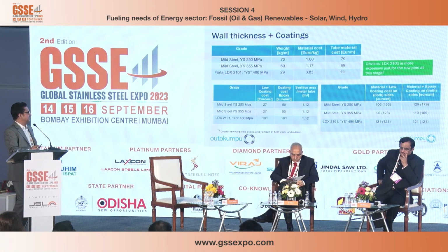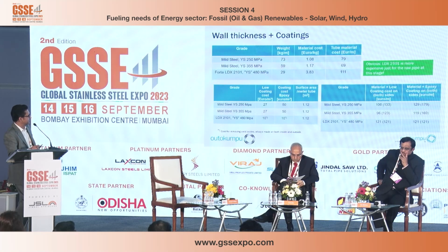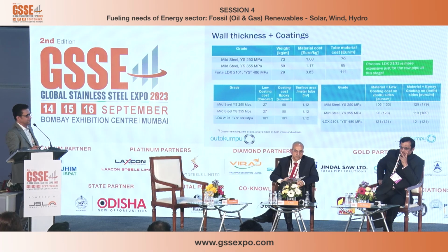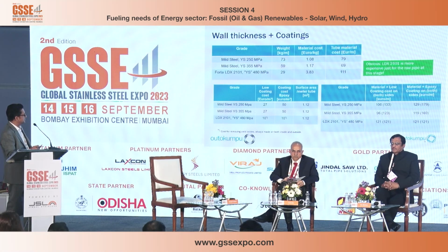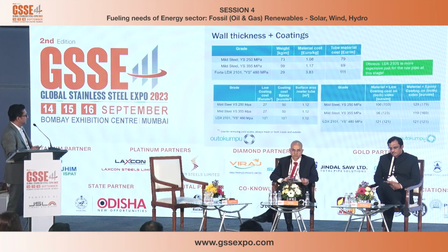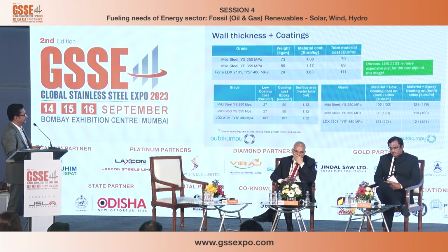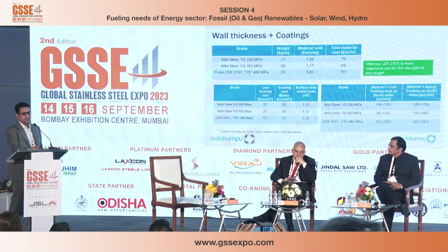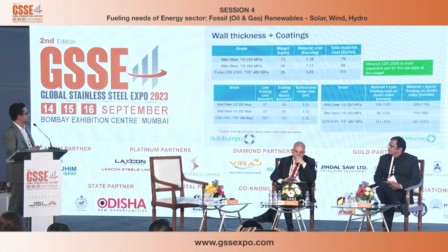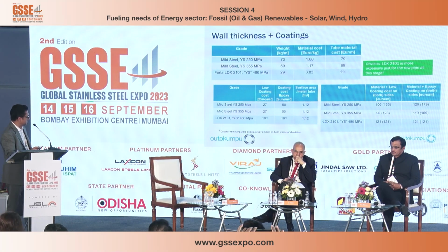For this size of the pipe, kg per meter, if you see, weight is 73, 59 and 29. Material cost 1.08, 1.17 and 3.83 euro per kg. Tube material cost is 79 for 250 megapascal strength, and for mild steel with 355 high strength is 69, and for duplex it is 111 euro per meter, which means duplex in the initial stage is still costlier than the carbon steel, whether it is low strength or high strength.